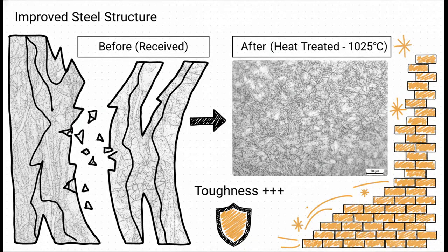And would you look at that? When we look at the images, you can see the heat treatment worked like a charm. On the left is the steel as it was received, with these big, stretched-out grains. And on the right, that's our winning 1025-degree sample. The structure is so much finer, so much more uniform. It is a much, much better brick wall.